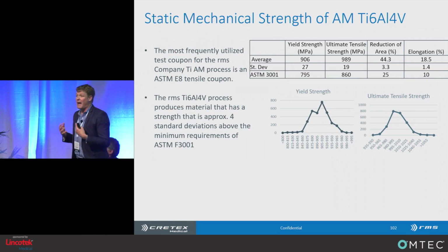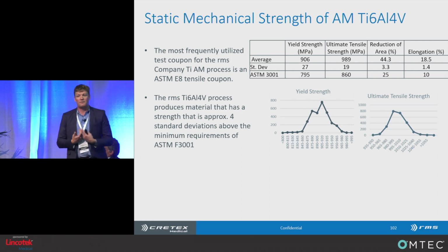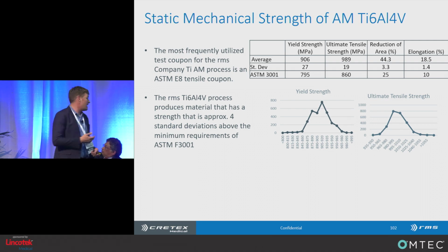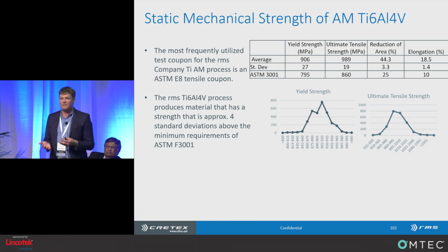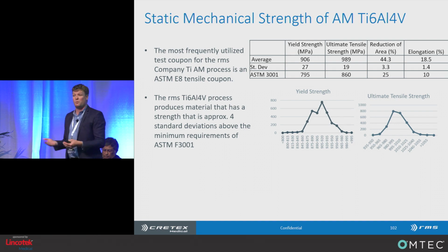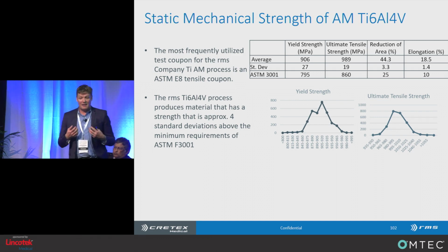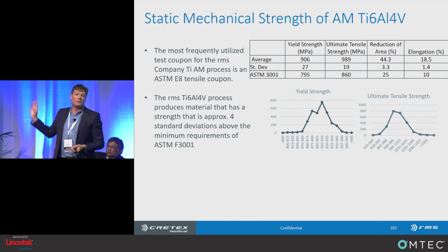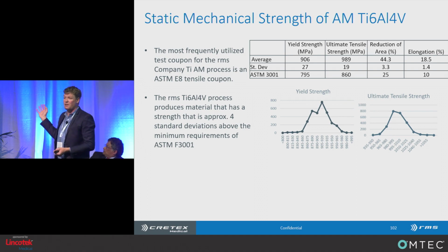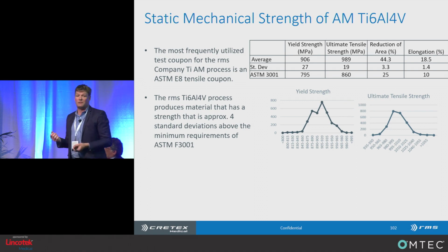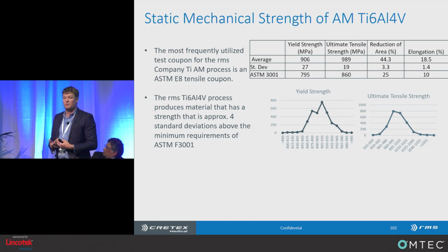Let's talk a little bit about static mechanical properties and how they relate to fatigue strength, right? As Mukesh pointed out earlier, there's this perception that additively manufactured Ti-6.4 is weak. In reality, you have a lot of influence on what the strength of that material can be, and generally it's pretty strong. We struggle to actually produce parts at the ASTM minimums, right? You can see the minimum strengths here and our averages and our process capability. In general, we're about 4 standard deviations above the ASTM F3001 requirements for mechanical strength, right?